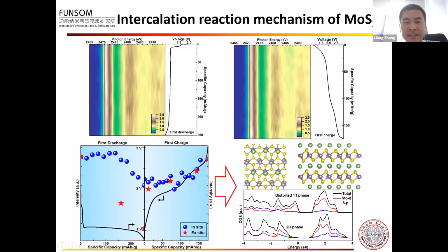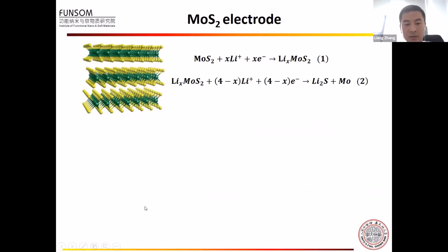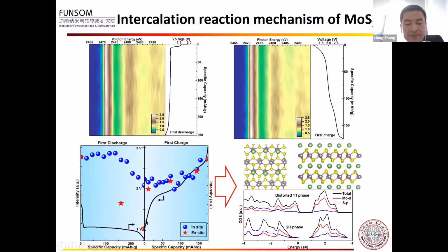This is the intercalation reaction result. Here, I show the contour plot with X as photon energy, Y as the state of charge, and the different colors indicate the different intensity. The spectral shape doesn't change very much during the charge and discharge process. To further analyze this data, we plot the intensity of the main feature in the sulfur K-edge results, and we also compare the in-situ results with the ex-situ results. Here the blue curves are the in-situ results, and the red are the ex-situ results. We can see that the lithiation degree is always higher for the ex-situ results.